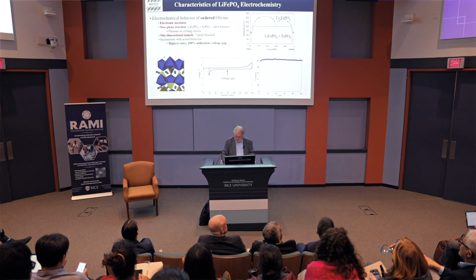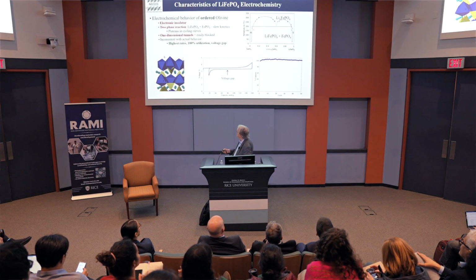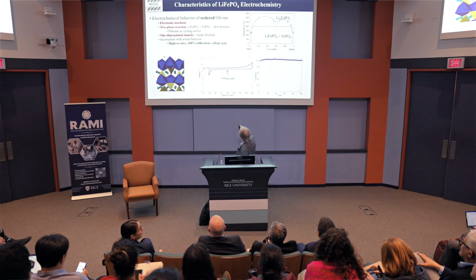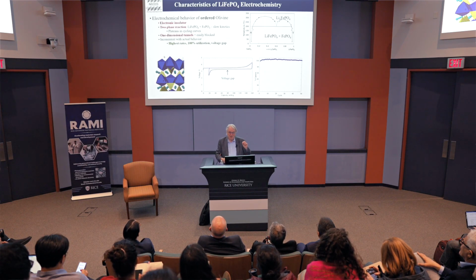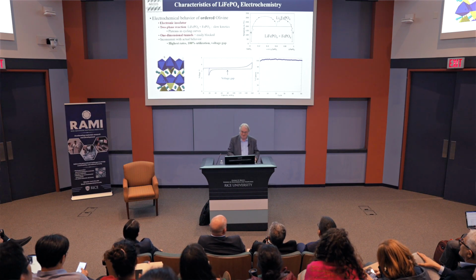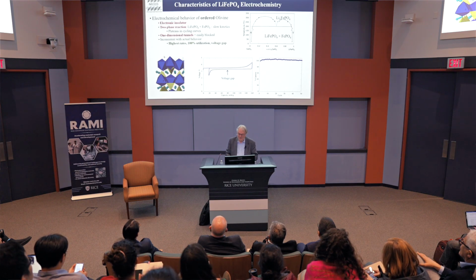And a strange thing in here, which we didn't understand for a long time, is this voltage gap. So the open circuit on charging is different than the open circuit on discharge. Okay. That shouldn't be the case, so we had to understand that. And this is the phase diagram. You can see you've got a bit of single phase here and a bit here. This is two phase in the middle.